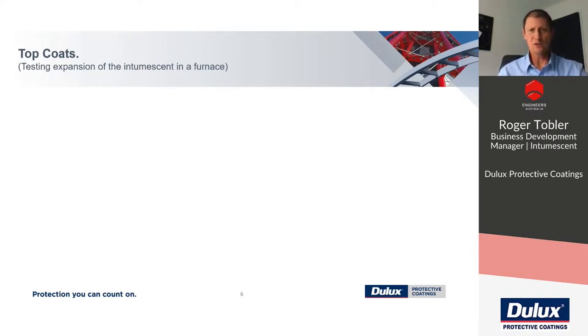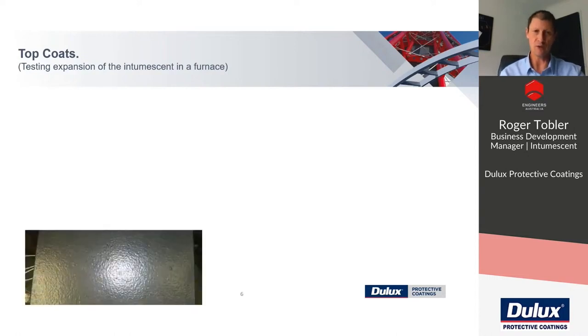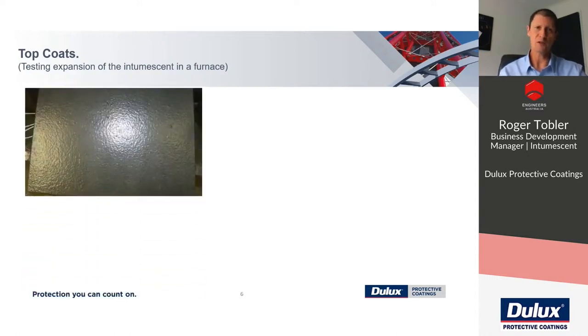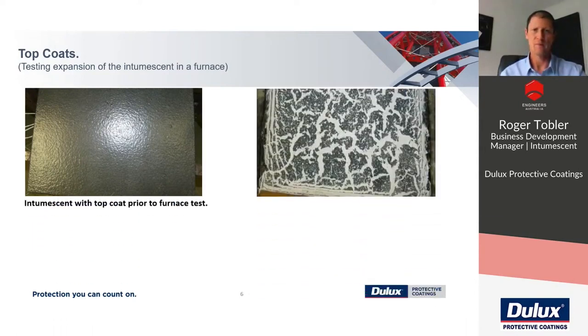So we're going to show you a few pictures of intumescents that have been tested in a furnace, and we've tested intumescents in conjunction with the top coat. The first picture shows you an intumescent applied at 1,000 microns before the test, not exposed to heat, and the top coat is applied over it. The second photograph, same panel, is post-exposure to heat in a furnace. There's a thermocouple attached to the back of the plate. The plate is heated up to 500 degrees Celsius and the time recorded.